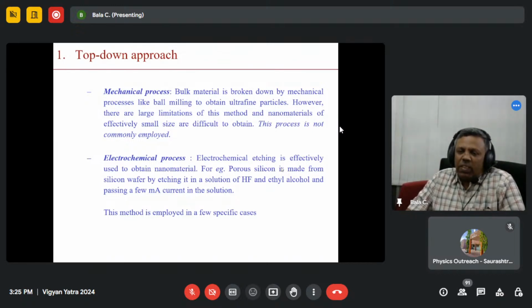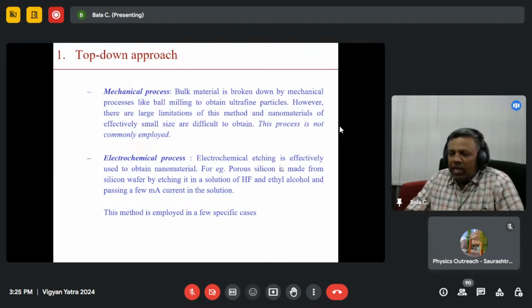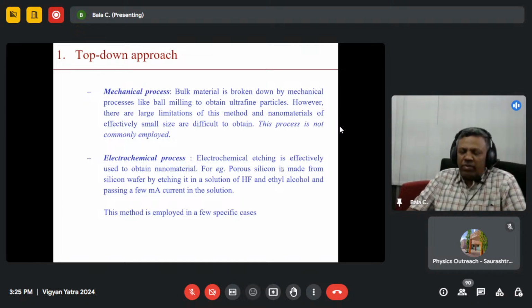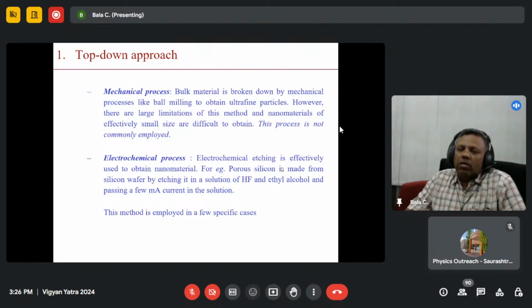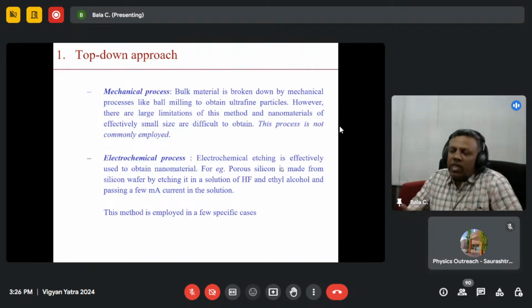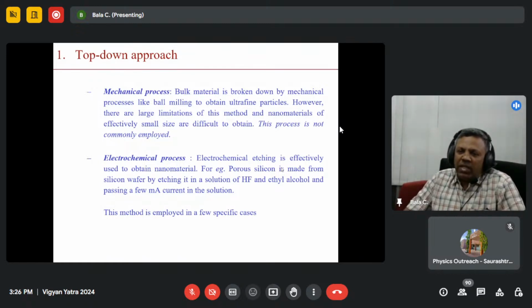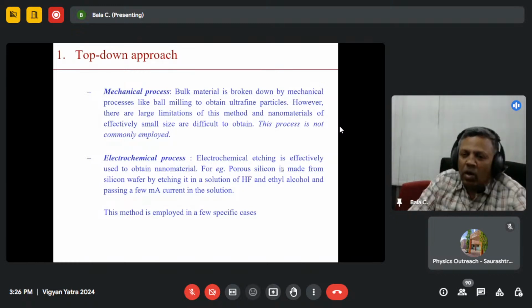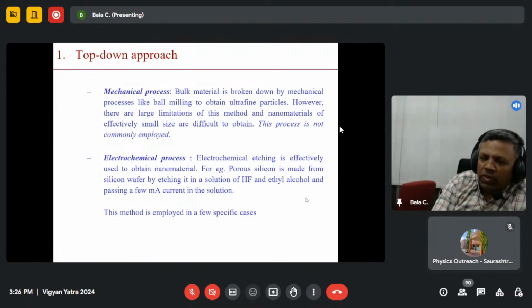The other process is the electrochemical process. For example, you have a bulk material, you start etching it out, or removing it cluster by cluster, or layer by layer. Finally what remains is a surface which has islands of small clusters, whose size would be in the nano range. Then you can call it a nanostructured material, for example, porous silicon. You take silicon, add hydrofluoric acid and ethyl alcohol and pass a current of a few milliamperes. The surface gets etched out, forming small islands in between, and these islands can give rise to nanomaterial properties, for example emission properties, red emission, orange emission, etc. So this is used, but as you can see, it cannot be used for every material. For some materials, yes, this can be used.